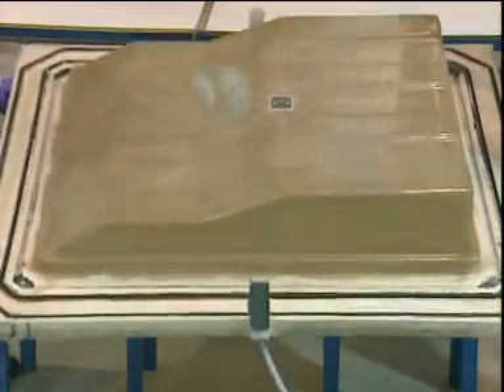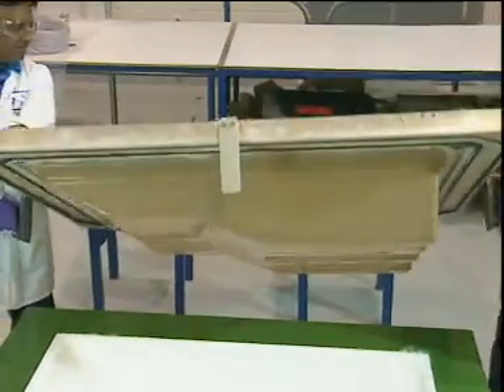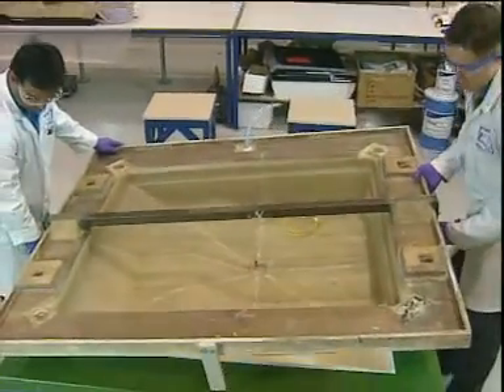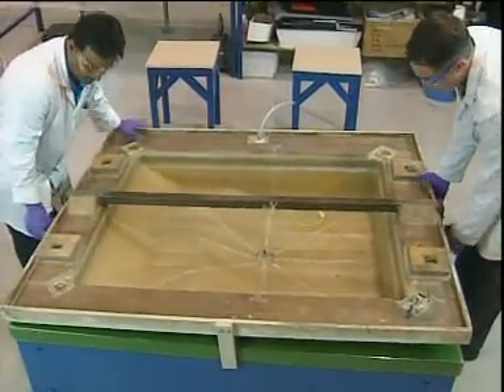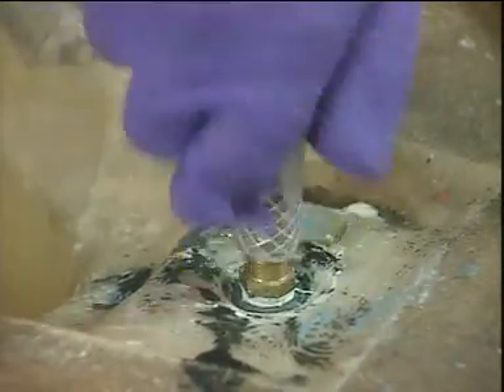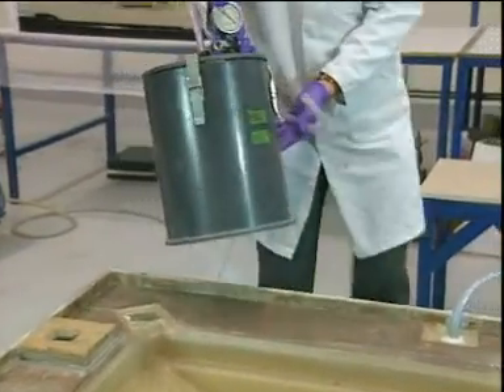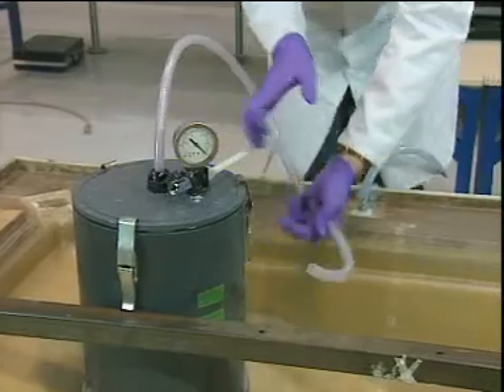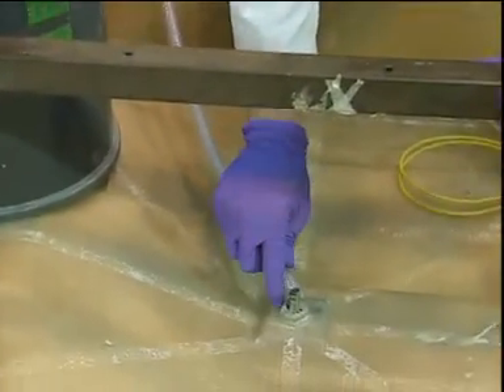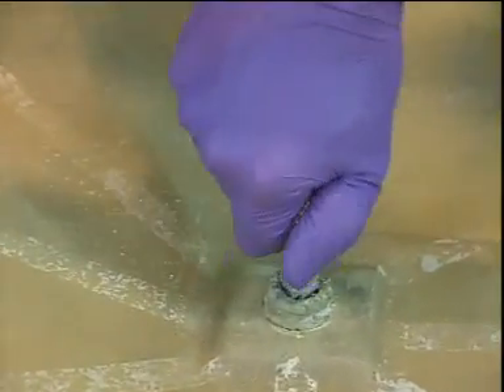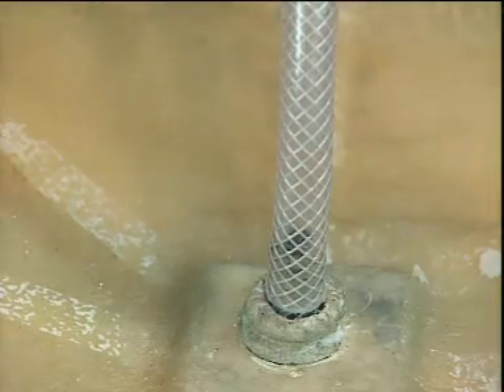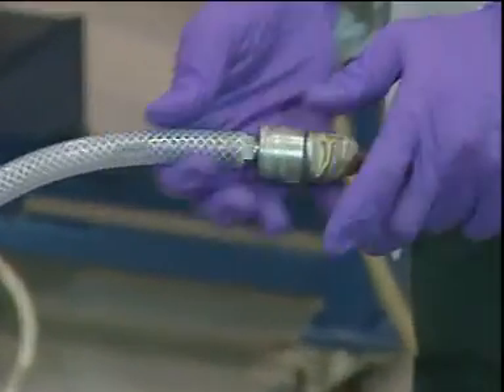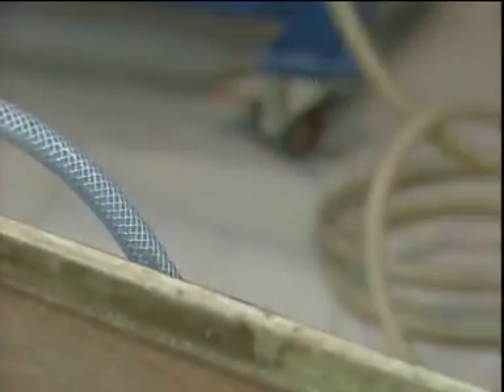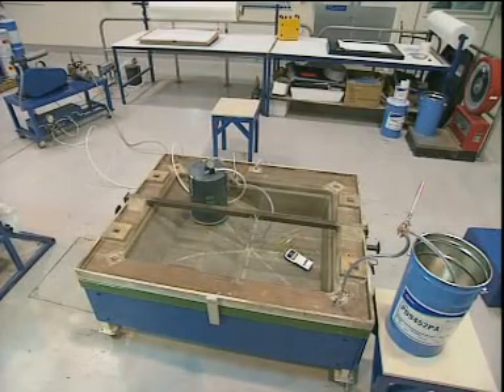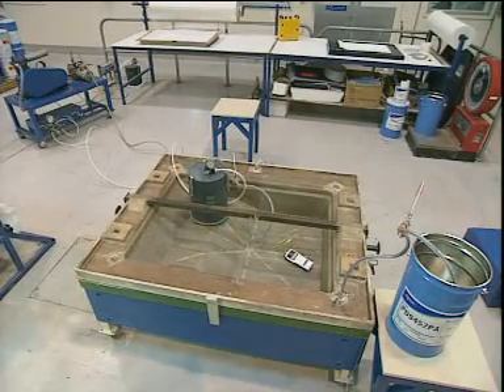A lightweight polyester GRP upper mold is then placed onto the reinforcement. The resin inlet and vacuum takeoff tubes are attached. A catchpot is used to ensure excess resin does not enter the vacuum pump. A full vacuum is pulled between the 2 seals to clamp the mold, and a second vacuum of 0.6 bar is drawn from the central point.